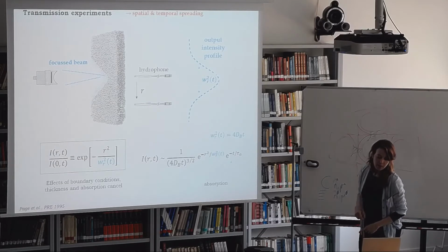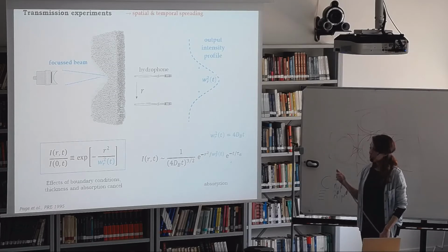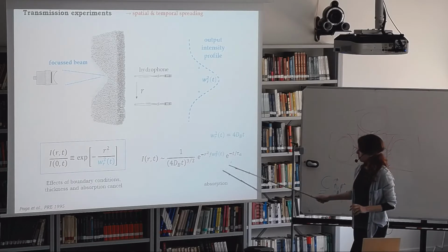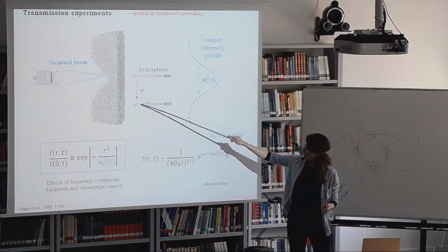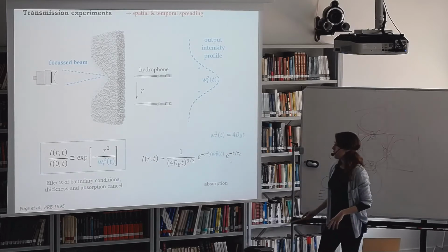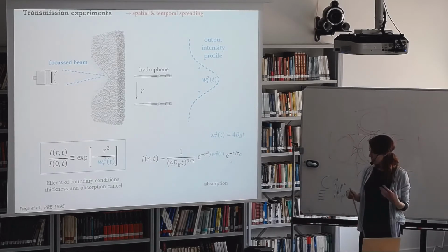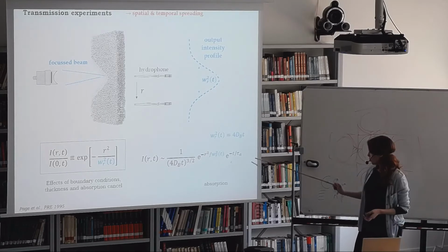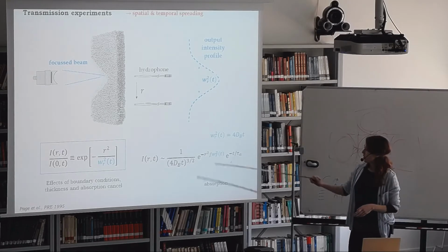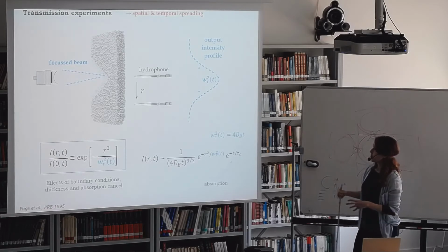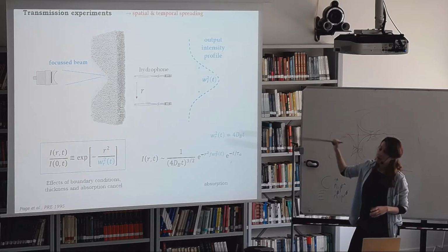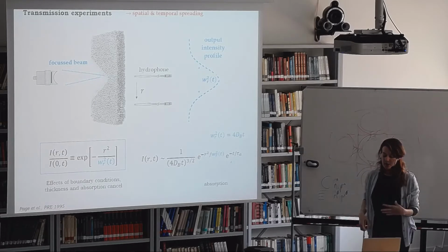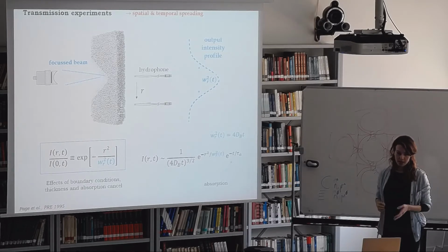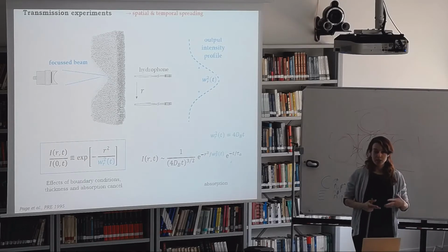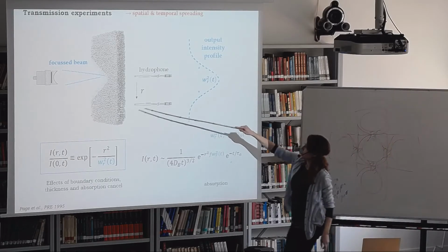What's especially important is that we can take the ratio of these intensities, the ratio of off-axis to on-axis intensities, and in doing so we cancel out most of the effects of boundary conditions, sample thickness, and absorption, which is super important, and we get a profile which really only depends on the transverse width, this width here, of the spreading intensity. So this lets us measure the width quite directly. This is a direct measurement of the spreading in the transverse direction, so the spreading throughout the sample like this.